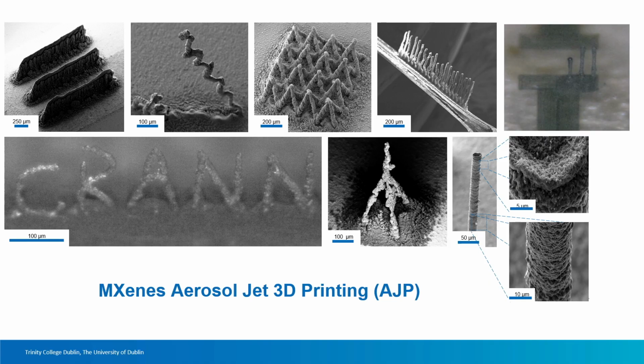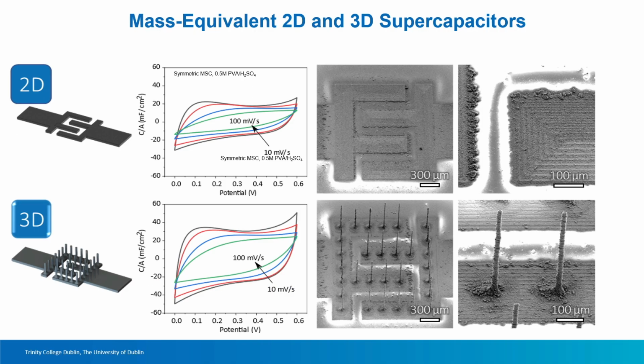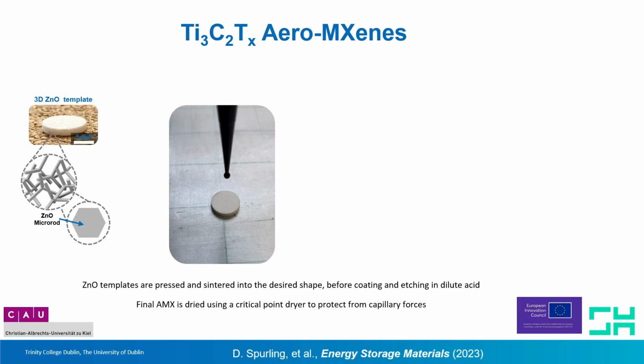They're pretty mechanically robust. And if you do that and compare, for example, the interdigitated devices that I showed you before with interdigitated devices with 3D pillars grown on, then you can see that you can actually improve the performance of the device by about 60 to 70% simply by adding these pillars to the device.